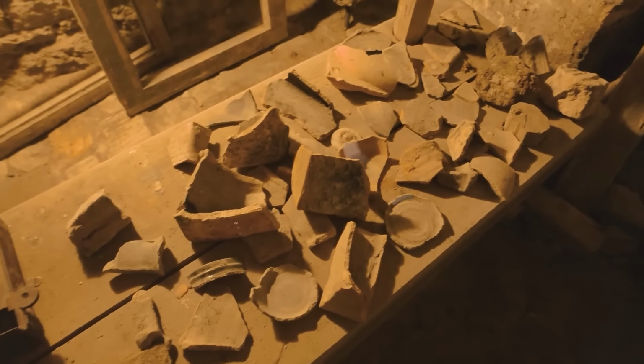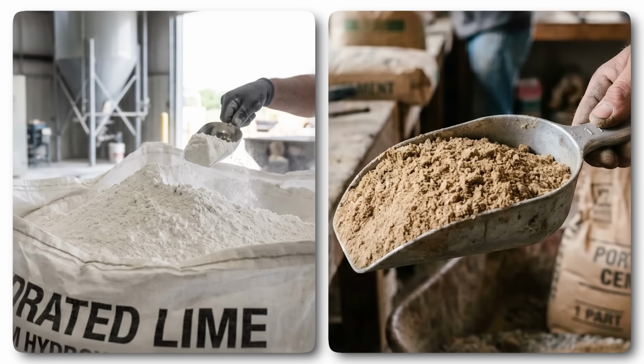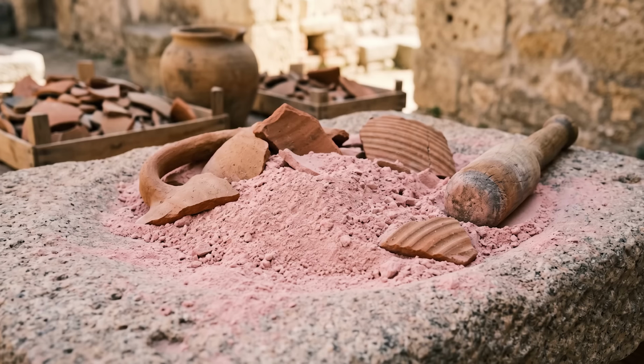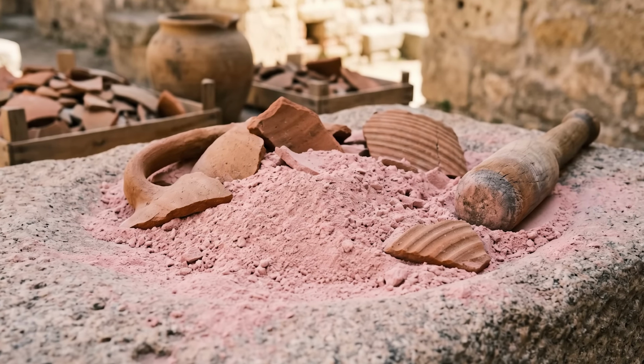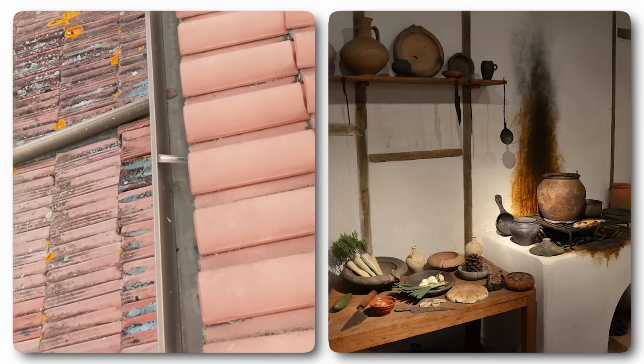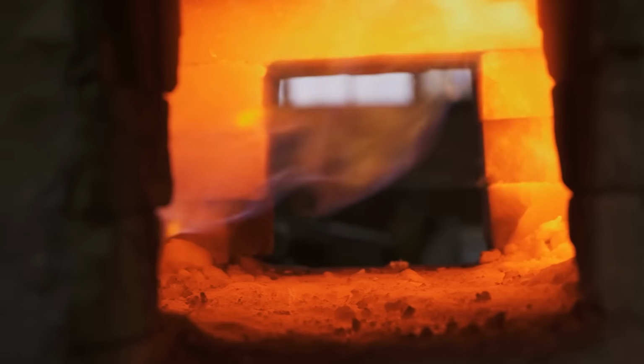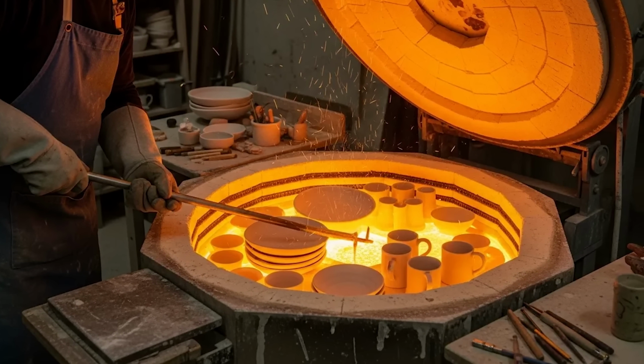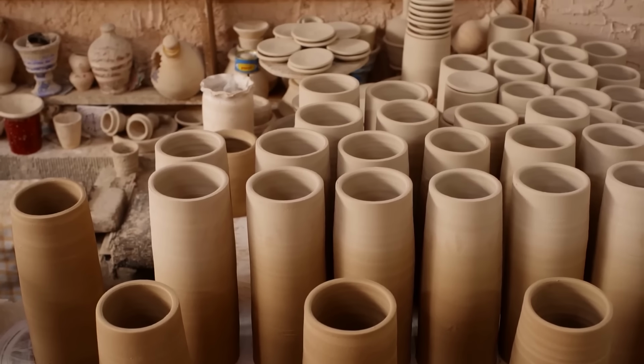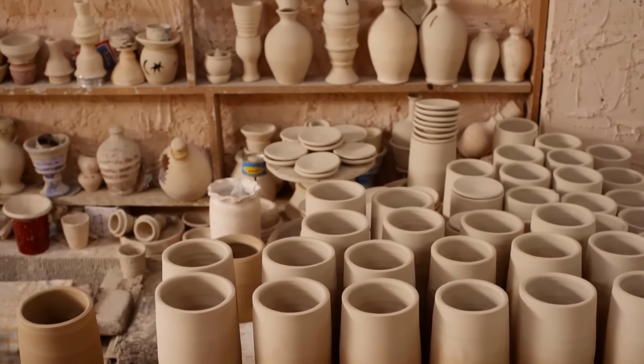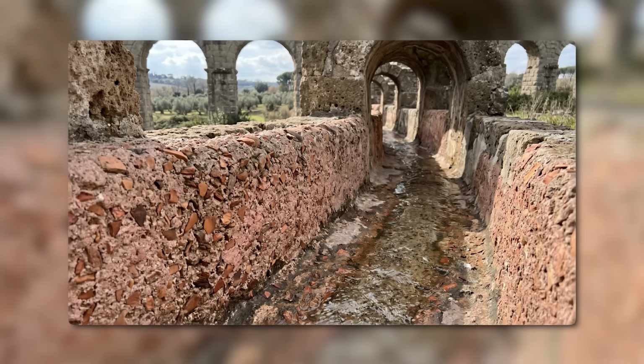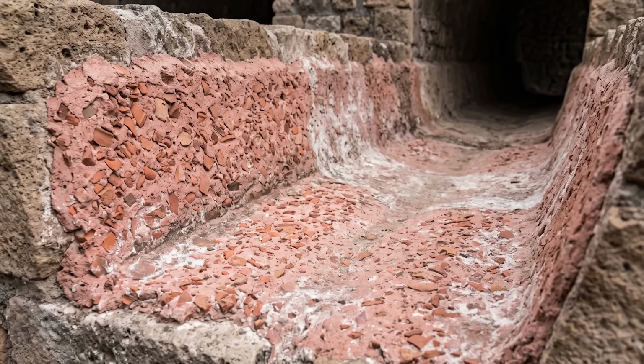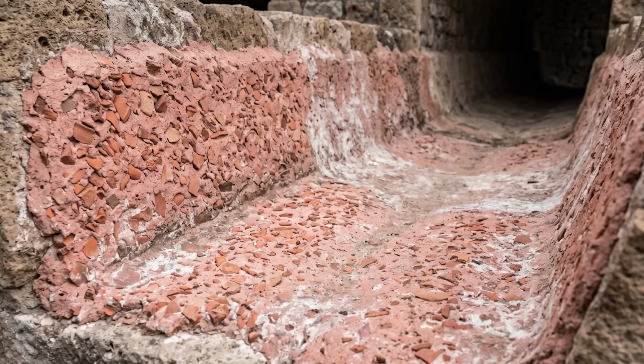3 parts crushed terracotta pottery, 2 parts lime, 1 part sand. The pottery was ground to a fine pink dust from broken amphorae, roof tiles, and kitchenware. When you fire clay above 800 degrees Celsius, the silica and alumina in it are partially activated, the same way they are in volcanic ash. Fired pottery dust is pozzolana you can make in any kitchen kiln. Cocciopesto is waterproof, slightly flexible, and self-healing through the same calcium carbonate mechanism.